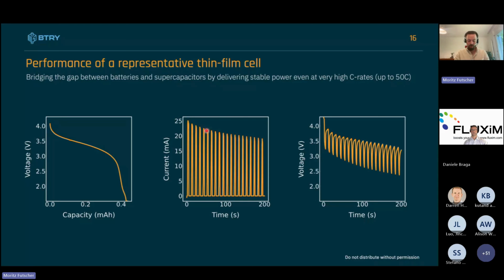C rate is how often you can charge and discharge a battery in 1 hour. So 50 is close to 1 minute. A C rate of 60 would be exactly 1 minute, and a C rate of 1 would be 1 hour. And you see that this cell with a very low capacity can still deliver very high currents, which really shows you the unique properties of this technology.